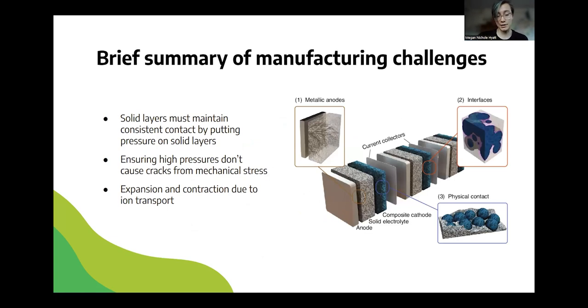Manufacturing processes of solid-state batteries need to take into account a few challenges, so I'll first summarize them here. The first challenge is that the anode, cathode, and electrolyte layers need to maintain consistent contact. Because there is no liquid electrolyte that will automatically fill the flatness deviation present on a surface, oftentimes high pressures are required to press the solid layers together for adequate contact. Speaking of high pressures, the second challenge is ensuring that the mechanical stress of this high pressure won't cause cracks in the solid layers. And finally, the expansion and contraction of the battery due to solid ion transport, leaving volume vacancies in the cathode, means that pressure between layers can't restrict movement of ions.